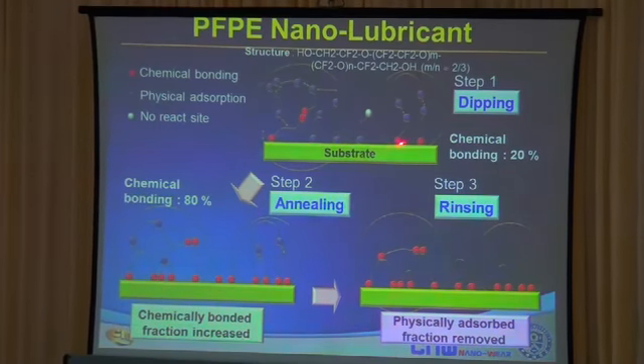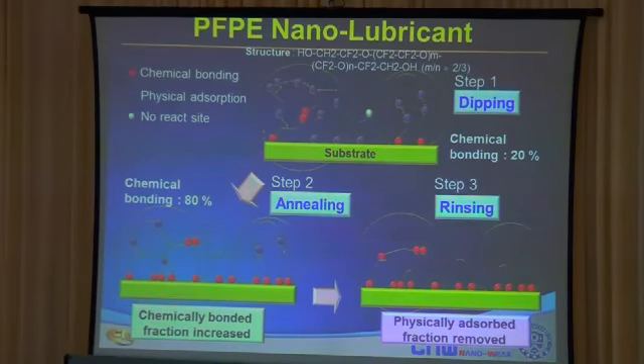But it's a little bit more complicated than that, because some of the molecules are attached to the substrate by way of chemisorption, in other words, by chemical reaction, so the bonding is very good. However, for most of the lubricant, it is attached to the surface by physical adsorption, by van der Waals forces, and these are very loose molecules that have mobility and can move around.